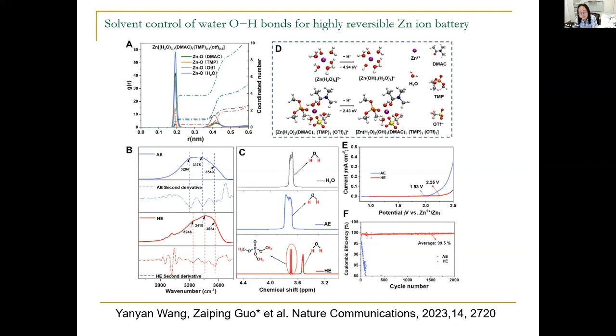proton in the water. So you can see from the FTIR spectra, the peak has an obvious blue shift, indicating the hydrogen bonding between water is reduced, but the oxygen hydrogen bond is increased in strength. Also from the NMR, we can see there's a shift of the peak relevant to water to a lower chemical shift, around 3.52 ppm, indicating the electron density increases. So the oxygen hydrogen bond becomes stronger. Due to the stronger oxygen hydrogen bond, the water becomes more stable. You can see it stays stable even when charged to 2.25 volts.